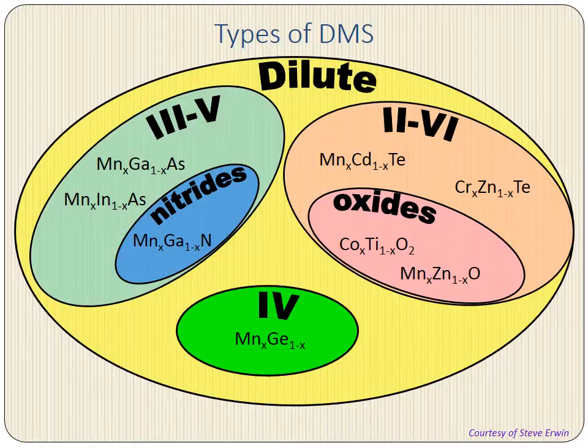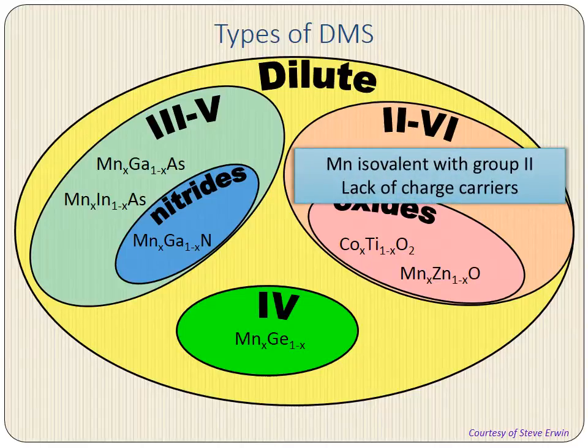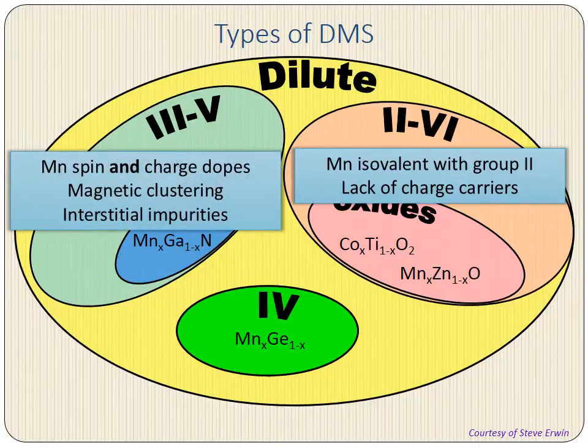One of the central areas of study within this field has been how to synthesize and engineer these materials, which contain significant complexity. In the 2,6 materials, manganese is isovalent with the group 2 ions, so there is a lack of charge carriers, and also robust ferromagnetism would be elusive. In the 3,5 materials, manganese both simultaneously spin and charge dopes the system, which complicates theoretical understanding. There is also a tendency towards the formation of magnetic clusters and also interstitial impurities, which also presents challenges for both theory and synthesis. Similar challenges also exist in the 4 group of DMS as well.